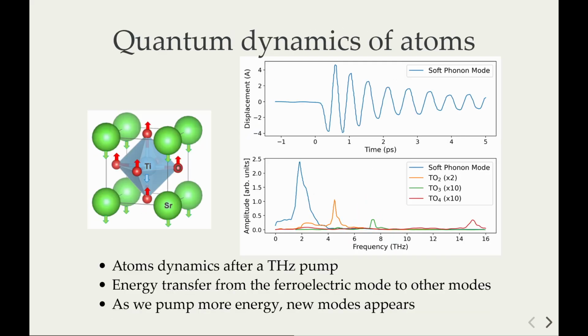We implemented this for extended solids and applied it to strontium titanate, running a virtual experiment of pumping strontium titanate on the softest ferroelectric mode. What happens is that even though our pump is in resonance only with this one phonon, when we do the Fourier transform of the motion of all ions, we see that all these other modes appear. Energy somehow transfers from the low frequency mode to high frequency modes.